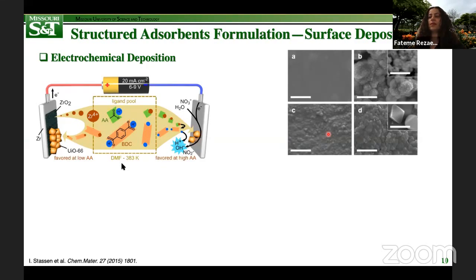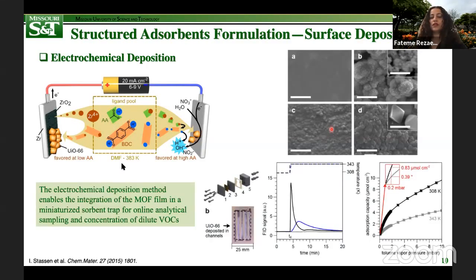Overall, the patented deposition capability of the electrochemical method enables the straightforward integration of the MOF as a sorbent film in a sorbent trap device for online analytical sampling and concentration of dilute VOC, volatile organic compounds, as you can see from these toluene adsorption isotherms presented here at different temperatures.